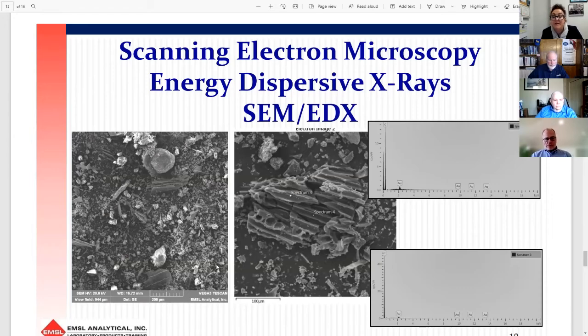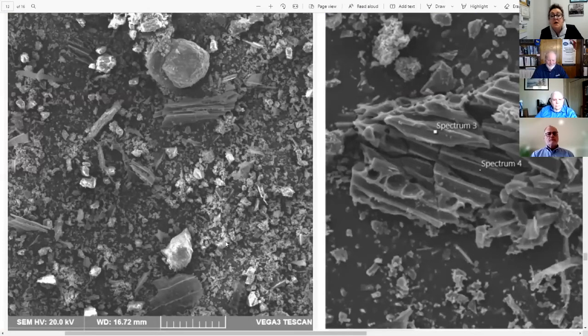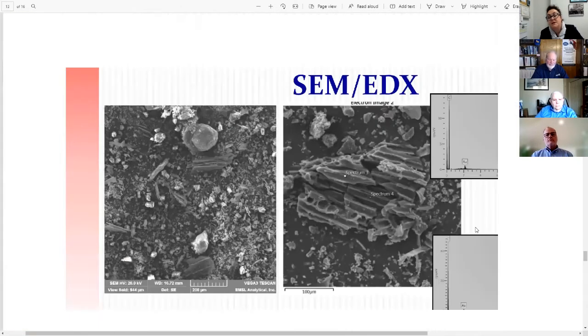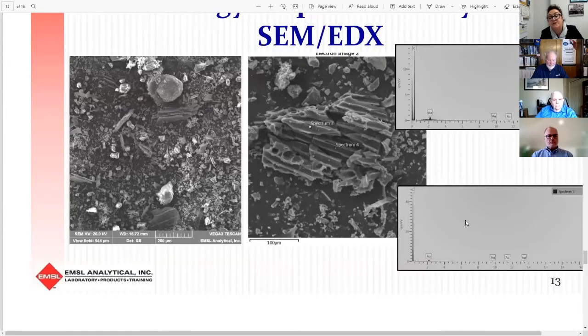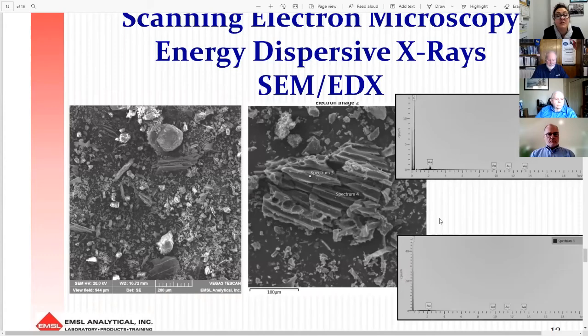And what is beautiful about SEM is that you can actually get the elemental composition in the same run. And on the left-hand side is a spectrum of the char that is shown in the image, and it only shows carbon, a high concentration of carbon. And gold, which is not part of the char. It's just a sample preparation that we had to apply. For this field, for example, it's also useful to derive a concentration. How much char do you have in the sample relative to other particles? And you can also determine what else the other particles are. It may be environmental dust. You may actually end up with some ash in here that is easier to see than in the PLM.